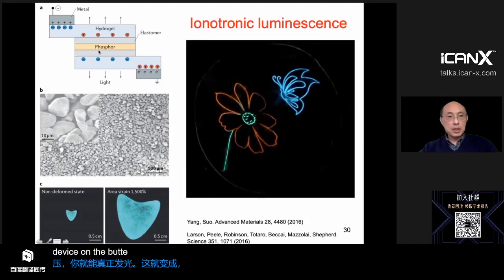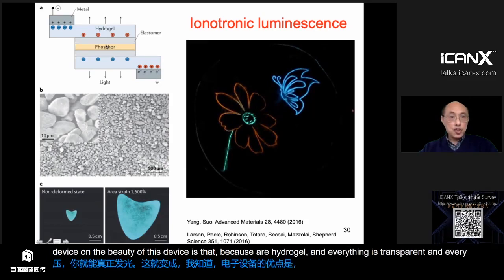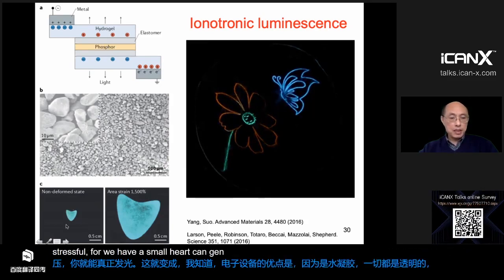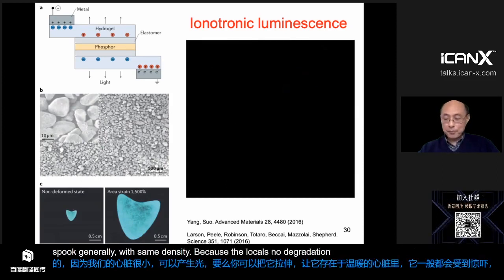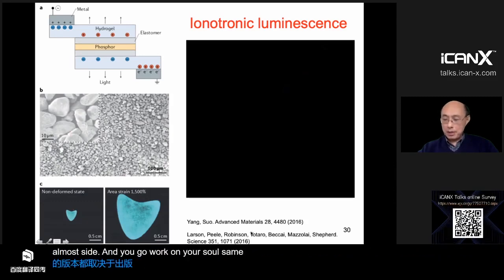So the beauty of this device is that our hydrogel and everything is transparent and everything is stretchable. So we have a small heart that can generate light, and you can stretch this to this enormous heart. It can still generate light with the same intensity. There's no degradation of intensity. So it's stretchable. We published this work in 2016, and another group, a friend, we actually know this guy, but we were totally independent, published almost identical work. Same year, almost exactly the same time. So it's a very exciting, good idea generated by two separate groups.